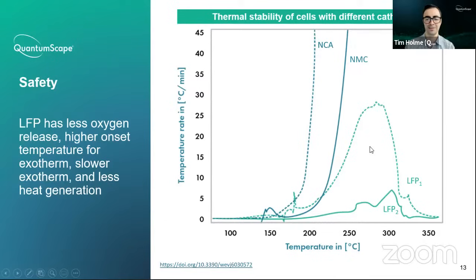This is an accelerated rate calorimetry test with 4 different cells. These 2 green ones are LFP-based cathodes. The 2 blue ones are more nickel-based cathodes. The cell is placed into a thermal chamber. The temperature is increased, and then no further heat is put into the system, and you measure how much the temperature increases in the cell. What you can see is that once you've increased the temperature of the cell to between 150 and 200 degrees Celsius, the cell can go into a self-heating mode where not much additional heat is added to the cell, but it can self-heat. And that's what these lines that take off show.